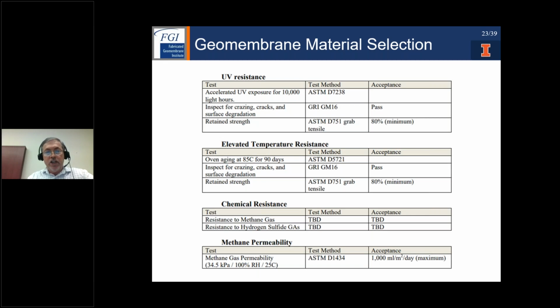We looked at the oven aging testing at 85 degrees Celsius or 185 degrees Fahrenheit for 90 days. And then again, we would at that point look for any surface cracking and surface degradation. And then as well looked at the retained tensile strengths of 80% minimum. The chemical resistance, we do note again that we need good resistance to methane and resistance to hydrogen sulfide. And at that point, we had not listed the test methods, but the next slide will talk about that. And finally, we do note the methane gas permeability to a maximum of 1,000 milliliters per meter squared per day. And many of our geomembranes can be well under that.